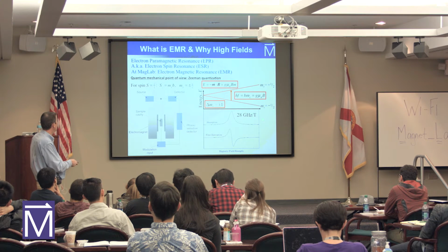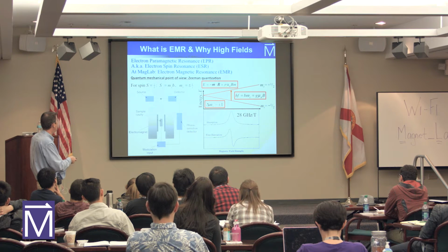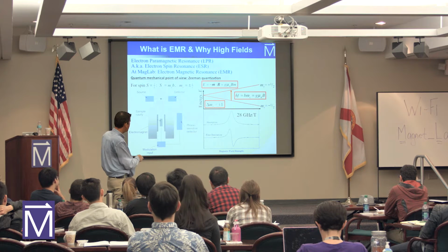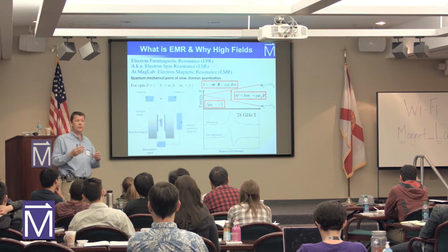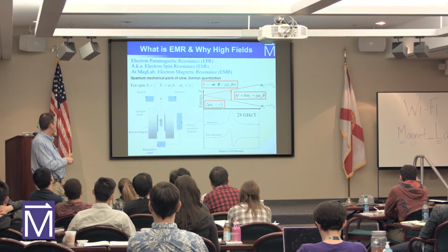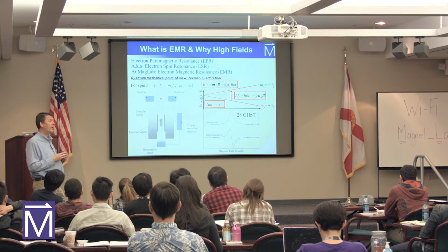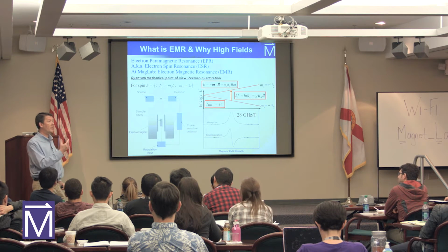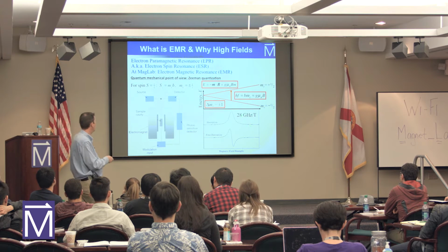And so we would see some absorption right when our Zeeman splitting matches the frequency of our photons. Of course, the line shape contains a lot of information as well. It's related ultimately to the lifetime of the excited state, but if you're looking at an ensemble, the line width can tell you something about the distribution of environments that the electrons reside in.